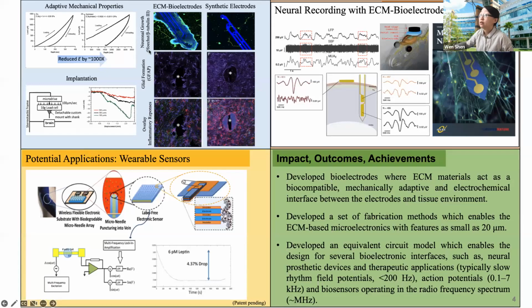After fabrication, we collaborated with our collaborator to check the biocompatibility of these electrodes. We found that neuron cells can grow very healthily directly on top of these ECM bioelectrodes, versus flexible electrodes that do not contain these ECM materials. Neurons cannot grow very well on those non-biological electrodes. We also implanted these electrodes in animals. We found that the conventional electrodes made of non-biological material form a scar around the implantation site, but for ECM biomaterials, we don't see significant scarring around the implantation site.